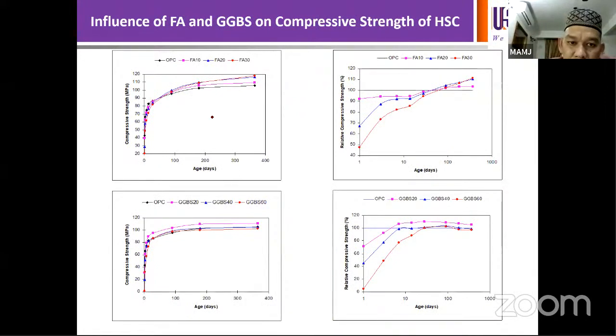Nonetheless, if we compare in terms of the fly ash concrete, the long-term strength, no problem. Long-term strength is very much achievable, greater than 100 megapascal in both fly ash as well as slag concrete. But when we want to see the early age strength, we have to see from the relative strength plot. So there is significant reduction in early age strength, in particular those containing the 60% slag and the 30% fly ash, for example. But in terms of long term, there is no problem, meaning that this material is able to develop strength greater than the control concrete, which could be linked to the pozzolanic reaction of the material with calcium hydroxide.